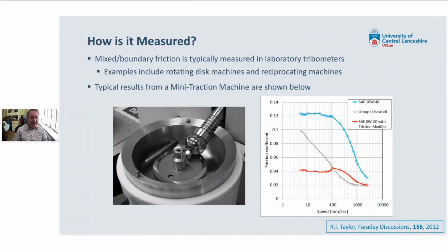So how can we measure mixed and boundary friction in the laboratory? We typically use tribometers of various types. An example shown here is a mini traction machine, which is effectively like a pin on disc machine, but instead of a pin, it uses a ball, and the ball can rotate or be fixed to slide. And this machine is filled with oil, and we're measuring the friction between the ball and the disc. The reason there's quite a lot of interest in this machine is that the disc speed can vary from just a few millimeters per second to a few thousand millimeters per second.